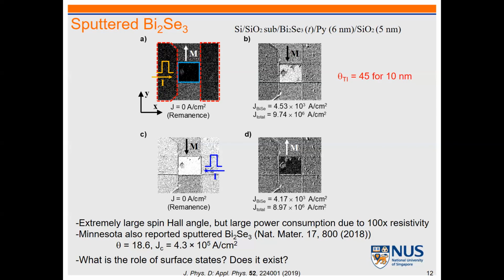As I told you, you can get any number, whatever you want. But the problem is this one is 100 times more resistive than my MBE sample. So that's why you have to roughly divide the spin Hall angle effectively by 100. So then nothing special. This is similar to what Jian-Ping Wang reported in his work. His spin Hall angle is like 18, and this is their switching current density. So basically, if you make a very realistic sample, in general you will have more scattering. Then what happens? Some portion of this scattering will be spin-dependent scattering, so it's not very useful.